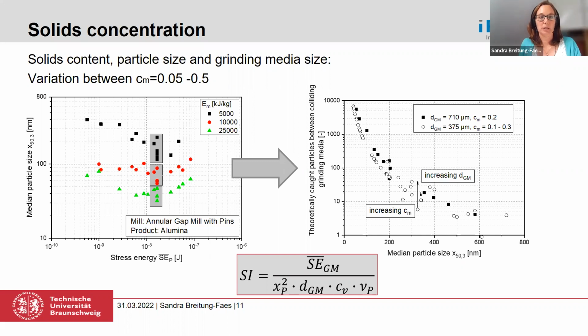So it's not possible to do it here with the original model because the concentration is not recognized at all. With this in mind, I calculated the theoretically caught particles between two colliding grinding beads. And here you can see pretty well the different influences with regard to the parameters we need inside our model. On the one hand side, you can see here on the x-axis the median particle size, which is decreasing or increasing depending on the side you look at. And you can see that with decreasing particle size, the number of caught particles increases.